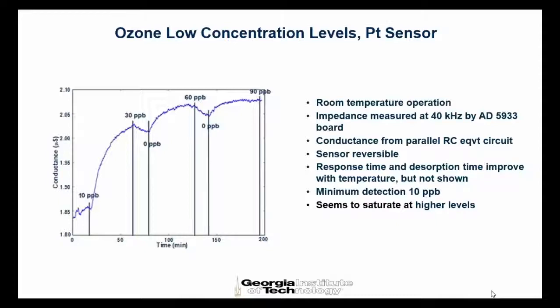What we found out is that the desorption is very, very slow. It takes 2 hours, and we could not sit in the lab and do that. Later, we found a solution. We had to increase the temperature. Instead of room temperature, we increased it to 75 degrees centigrade, and then we could make these times shorter. But you can see that the sensor is acting like typical carbon nanotube sensors. Good absorption, tending to dissolve to baseline, but we didn't go all the way. So that convinced us that the sensor is working.